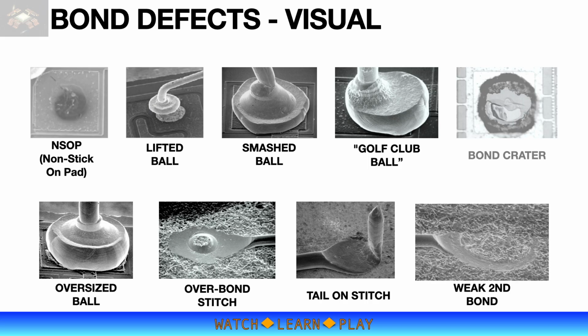Bond crater is a defect where part of the aluminum bond pad or metallization came up with the smashed ball, exposing and damaging the oxide layer underneath, which looks like a crater. This defect is typically associated with bond parameters being too high or not optimized. Some devices are more prone to bond crater than others. In this case, it is quite important to optimize bond parameters to address the problem.